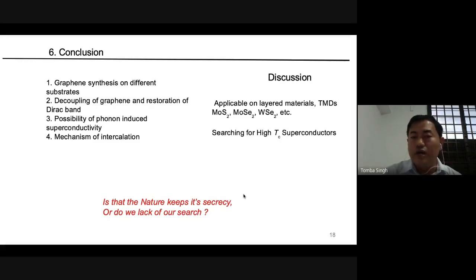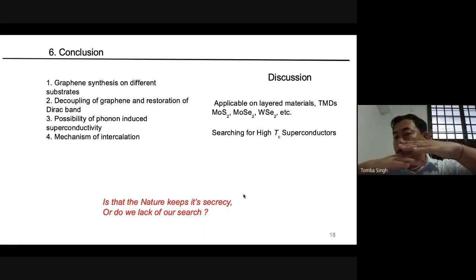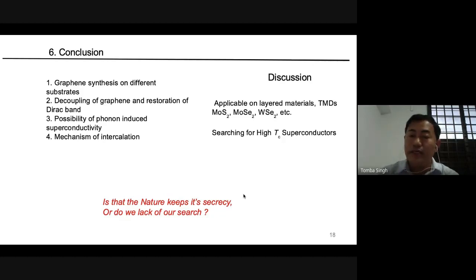We have discussed. I want to have a short discussion on where we can use our intercalation technique. Definitely, for layered materials like transition metal dichalcogenides, say MoS2, WS2, these TMDs, if we introduce intercalated layers, then we can single out one layer or monolayer. Then we can have the electronic properties of the monolayer or bilayer that are much different from the bulk property. And in the case of GICs, if we intercalate, then there is a possibility of inducing superconductivity. So in the future, there is a chance that we could have superconductors at high transition temperatures, and we could have better superconductors.